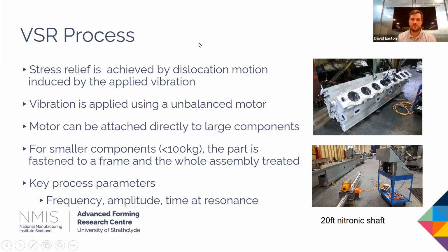So for smaller parts, it's as simple as fixturing parts onto, say, a table, and for larger parts all we do is attach the vibrator straight onto the component itself. So it's much simpler perhaps in setup than some of the heat treatment. The key parameters we're looking at are the vibration frequency, the amplitude, and the time at resonance.